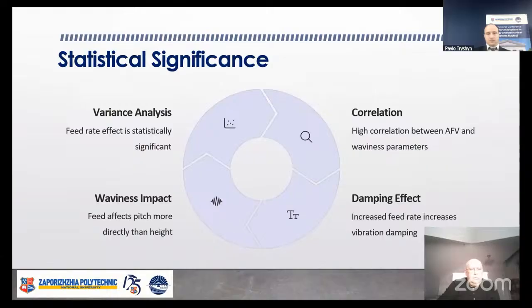So, some resume concerning statistical significance. Variance analysis shows that feed rate effect is statistically significant. Correlation. High correlation is observed between AFV and waviness parameters. Waviness impact. Feed affects pitch more directly than height. And the last one, damping effect. Increased feed rate increases vibration damping.